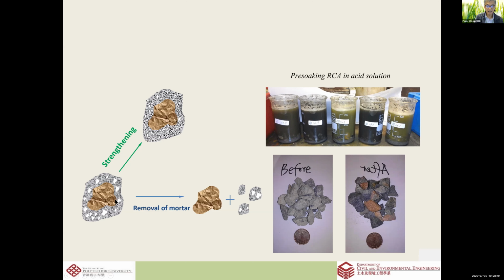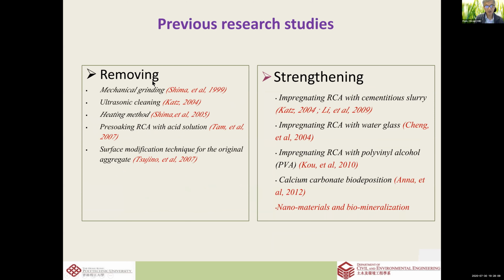So there are a number of methods of removing this mortar. There are mechanical methods as well as strengthening methods. Removing using grinding, ultrasonic cleansing, heating. Heating means heat it and cool it. Because of this thermal expansion and contraction, the mortar will break because of the thermal incompatibility between the natural aggregate as well as the old mortar.